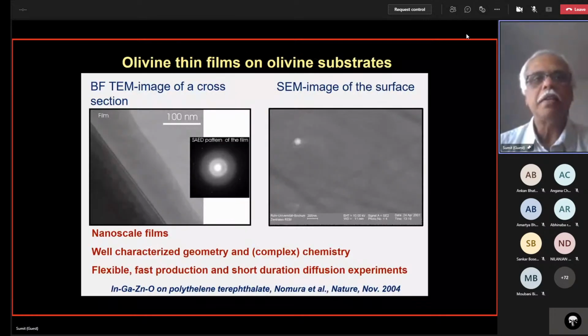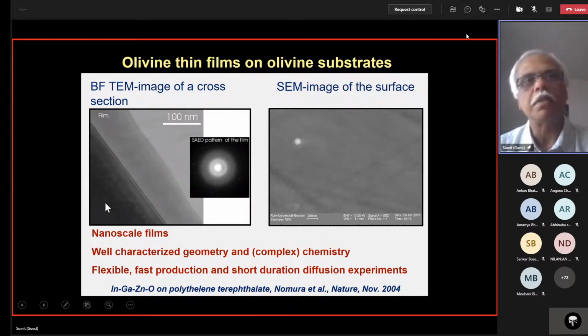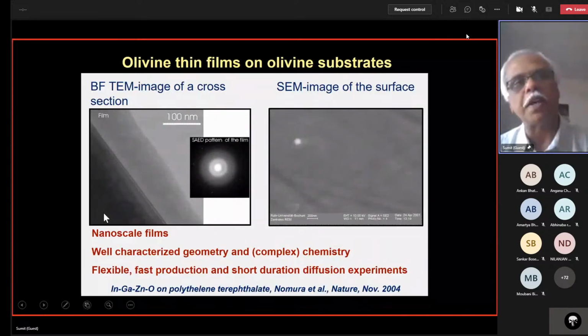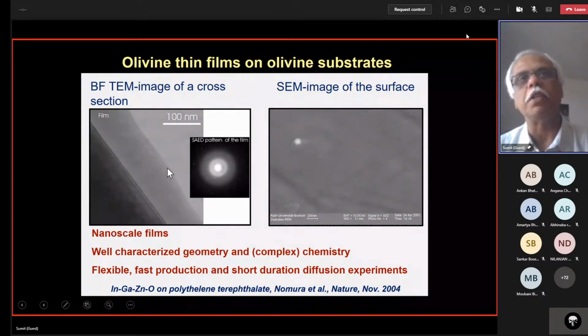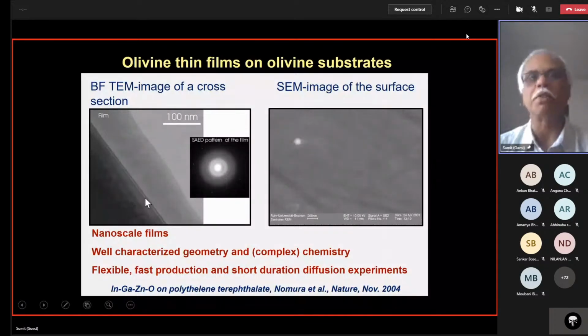This is what the things look like. This is now a thin film again of olivine on olivine. I just happen to have a lot of pictures of those because we've worked a lot on olivine. So this is now your forsterite 90, the dark thing here is forsterite 90 olivine, on which you have produced about a 100 nanometer thick film of an olivine of a different composition. So this is now two olivines forming a diffusion couple, just like you were seeing the two pyroxenes before, or the garnet and pyroxene and the garnet and biotite and so forth. And if you look at this thing from the top, you see absolutely nothing. So this is a very flat, very thin material.